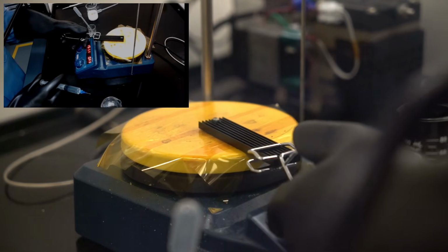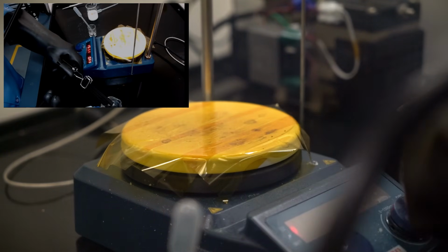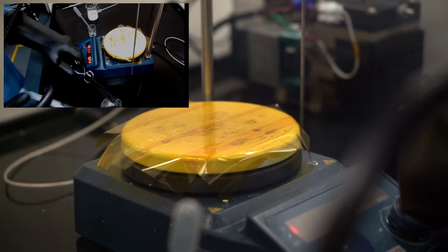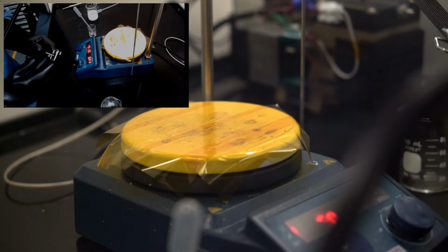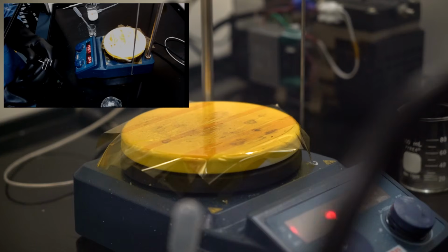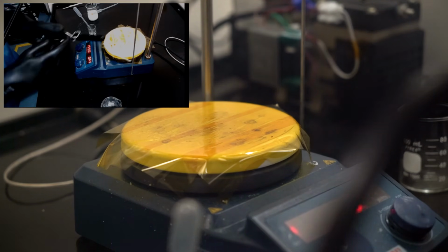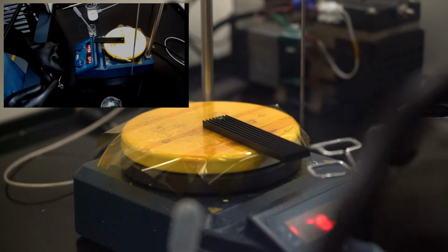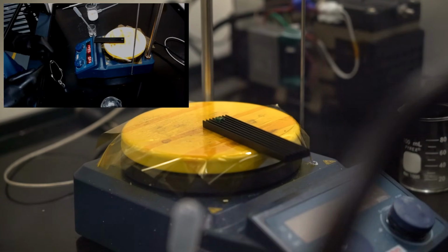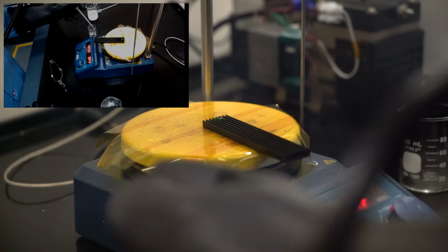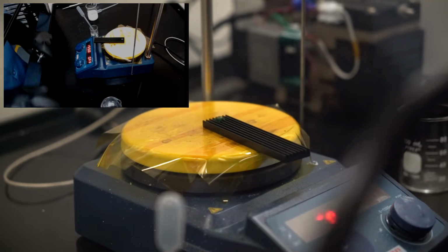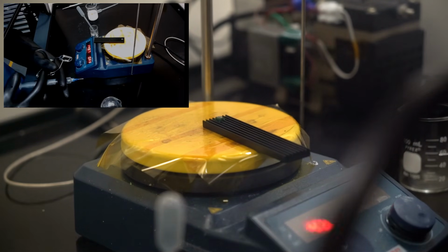We do also want to use a large quantity of solvent during the rinse cycle. The reaction with any residual acid is somewhat exothermic, and so to avoid any unwanted self-heating or possibly even ignition, we want to make sure that we flood the sample with solvent and bring the temperature down quickly rather than letting it sit there and react slowly with just a few drops of solvent. Not that it would be the end of the world if there was a small amount of exotherm going on there, but it would certainly damage the sample.